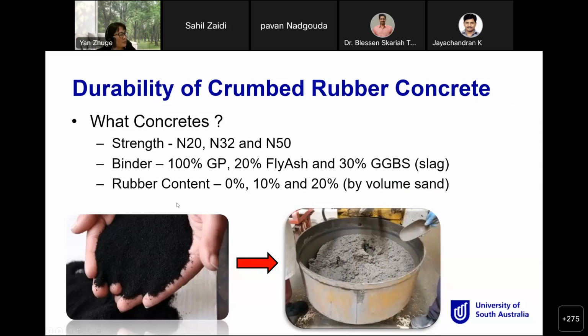Okay, so for the concrete, as I mentioned before, we have low strength concrete, 20 megapascal. We also did a medium range, 32 megapascal. For comparison, we did high strength, 50 megapascal as well. And for the binders, I said we have 100% Portland cement. We have another group of samples with 20% fly ash, and another group with 30% slag. So we have 3 different groups. And for the rubber content, we have 10 and 20% by volume. So these are all the mix designs we did for the durability test.